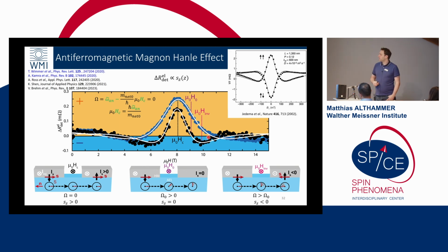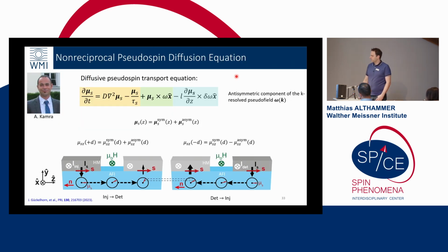And this is reminiscent of the electronic Hanle effect that you can also investigate if you do spin transport, with the main difference in the end that here our magnetic field really tunes this precession frequency via the canting, while there it's a transversally applied magnetic field that leads to a precessional motion of the electron spins in the structure, where you can immediately start at 0 magnetic field to reduce the effect.